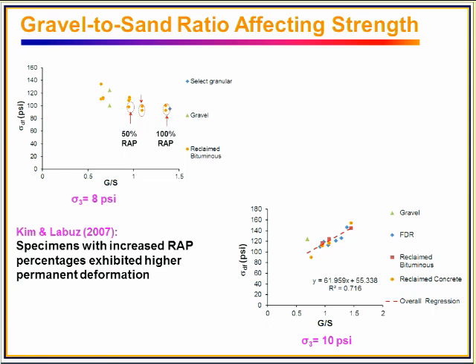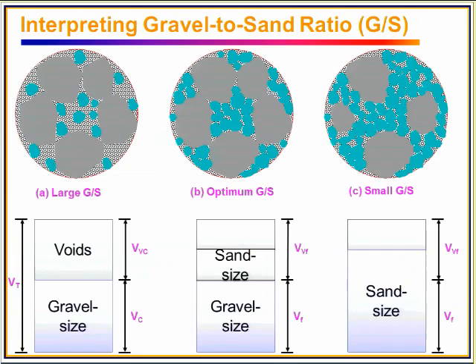shear strength behavior. So we were guessing that the similar peak deviator stress at failure may be due to the GS ratio, because if you reach the optimum GS ratio, then the shear strength behavior can be improved. This is an assumption we made, and then we tried to confirm this assumption from our own database and external databases.